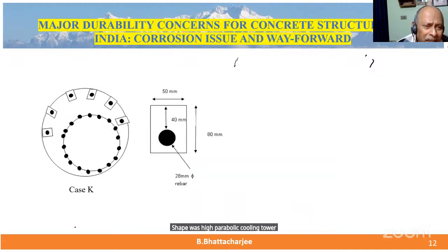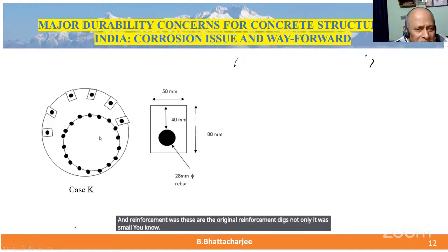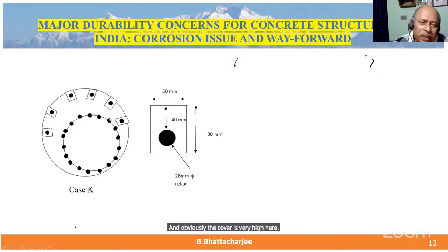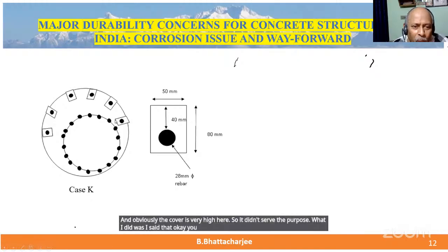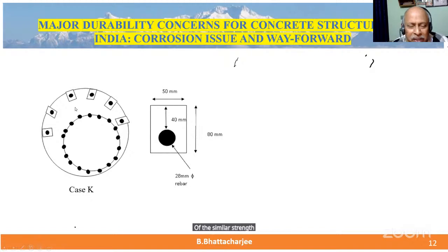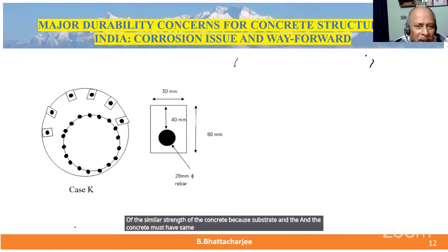And inclined. And the reinforcement was, this is the original reinforcement cage. Not only was it small, its diameter was much less, it got shifted to one direction, and obviously the cover was very high. So it didn't serve the purpose. What I did was I said, okay, you drill a hole here, cut a hole rather, groove it, and put epoxy of similar strength to the concrete, because the substrate and the concrete must have the same, and put in rebar of the same diameter, same type as much as possible.